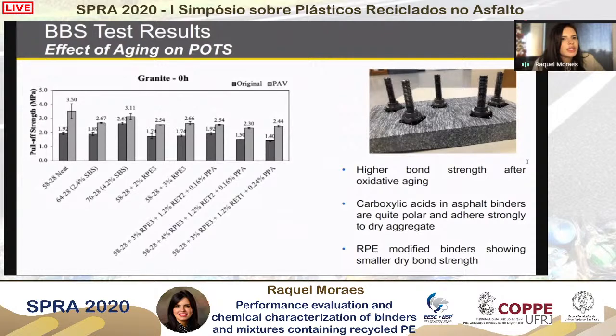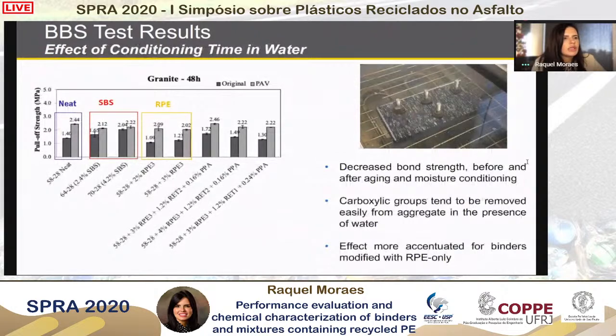RPE modified binders are showing smaller dry bond strength. Then we evaluate the BBS after the samples using the BBS. We evaluate the samples after being submerged in a water bath for 48 hours, before and after aging. And we can see a significant decrease in the bond strength before and after aging, considering moisture conditioning.